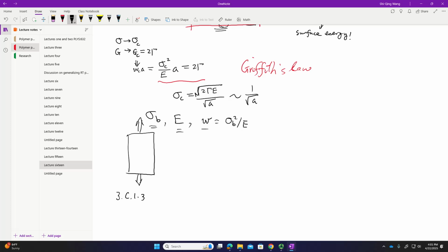Window glasses, apparently, I'm going to save some time, do have flaws. Of what size? To reduce window glass from 7 gigapascal to 200 megapascal, it just turns out to have flaws of a size in the micron range or so.